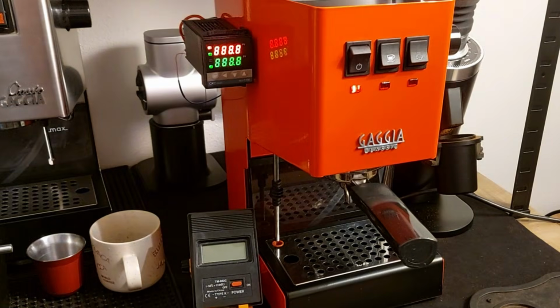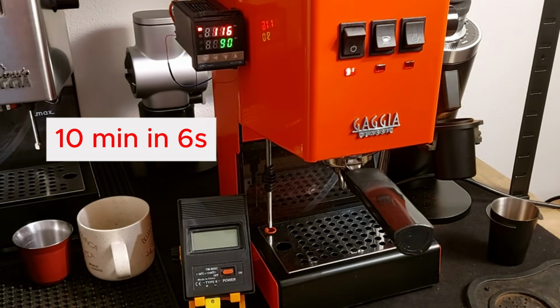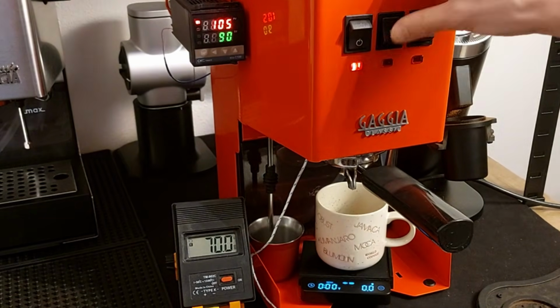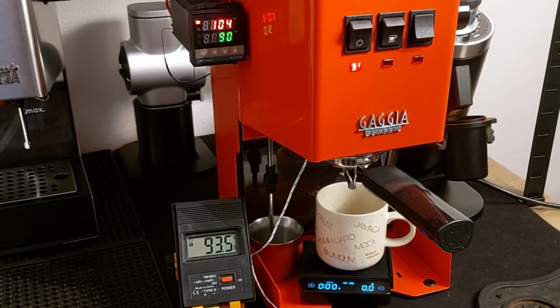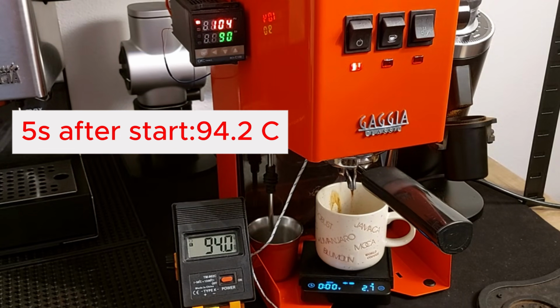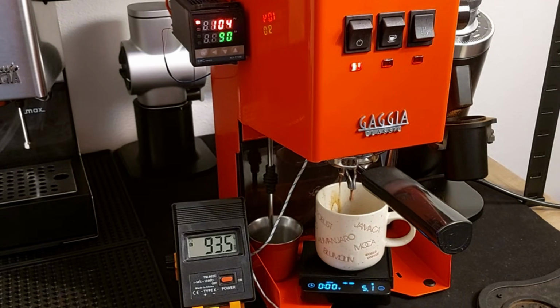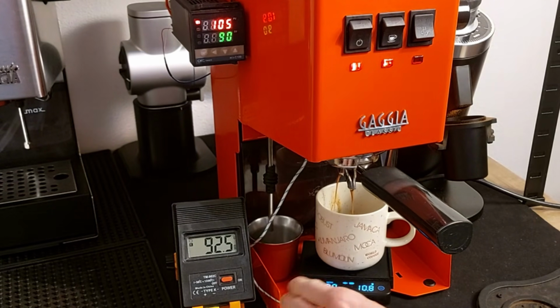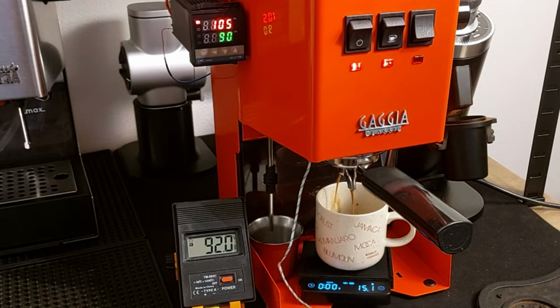I started my shot without pre-flushing exactly at 10 minutes and 38 seconds. The initial temperature after stabilizing after 5 seconds was 94.1 and the minimum was 91.6 degrees. It's only 2.5 degrees difference in 25 seconds. 19 grams in, 39 grams out. And for the majority of the beans, this temperature will be perfectly okay, in my opinion.